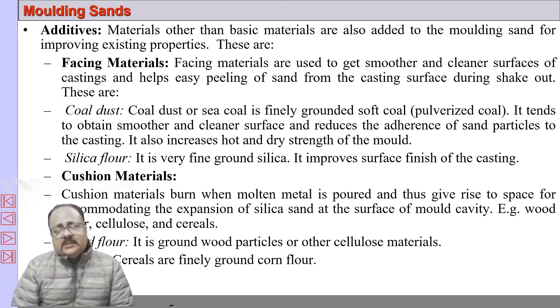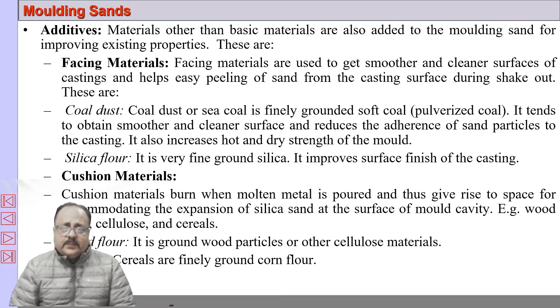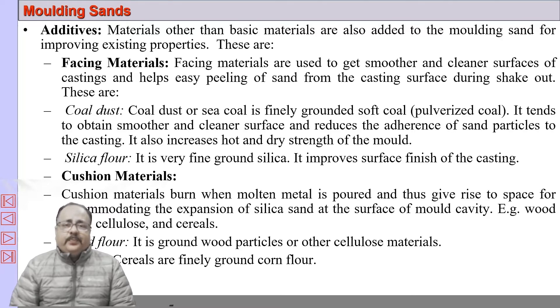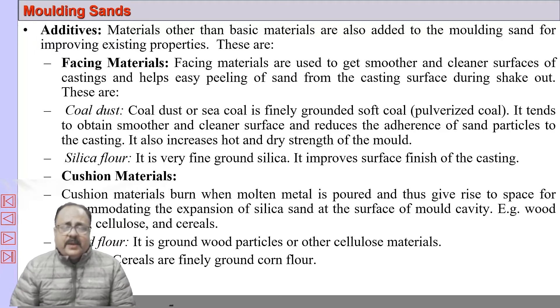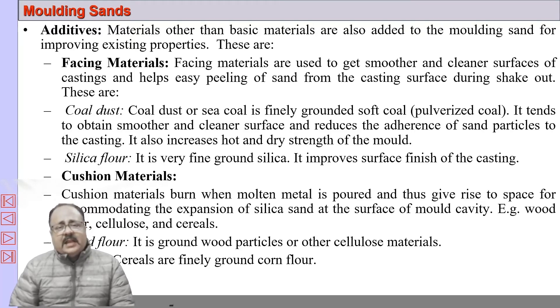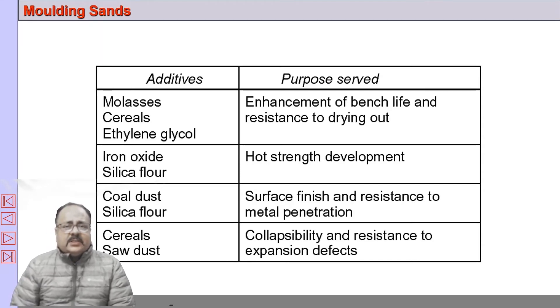Cushion materials are also added. When molten metal is poured in the mold cavity, the temperature is extremely high, causing individual sand grains to expand. If the sand cannot find space to expand, the mold will crack and the shape of the casting will be spoiled. Therefore, cushion materials like wood flour and cereals are added. When temperature increases, these cushion materials burn, gases are evolved which pass through the vents, and the burning creates space for the molding sand to expand.